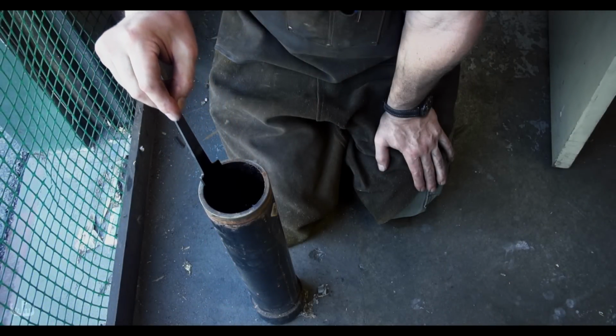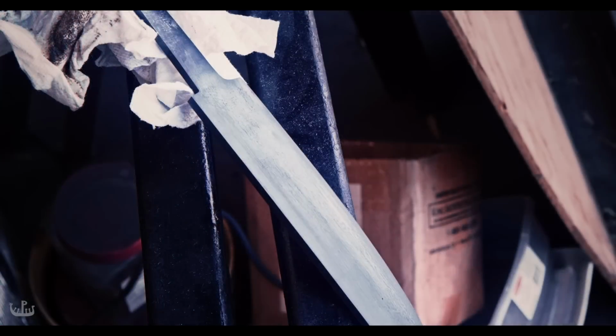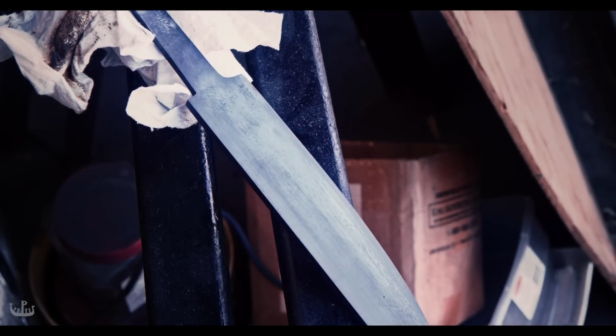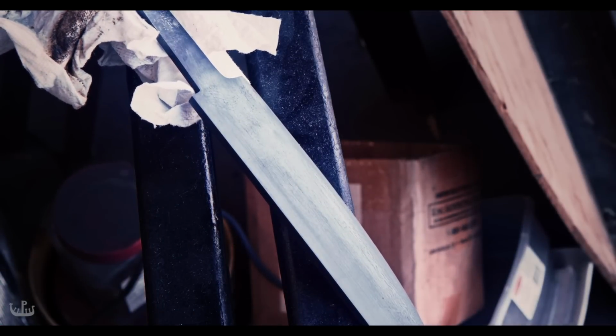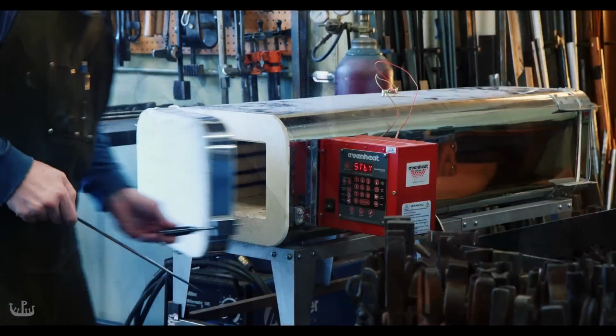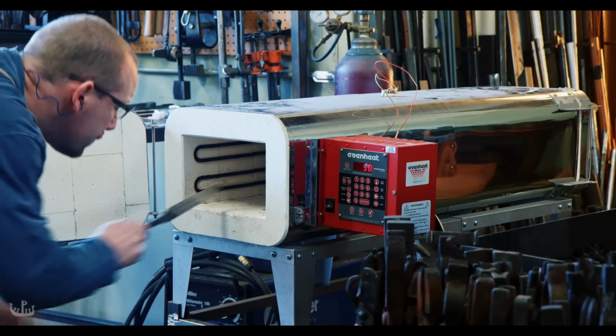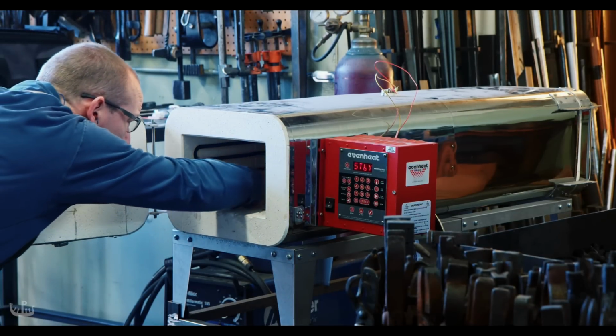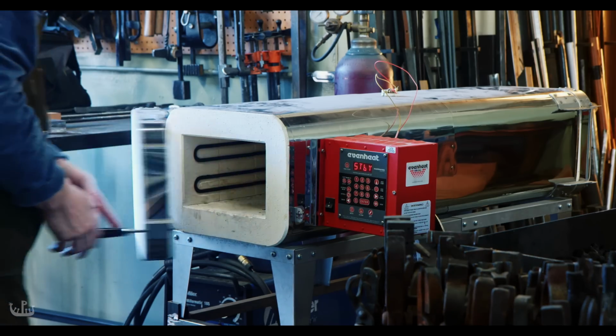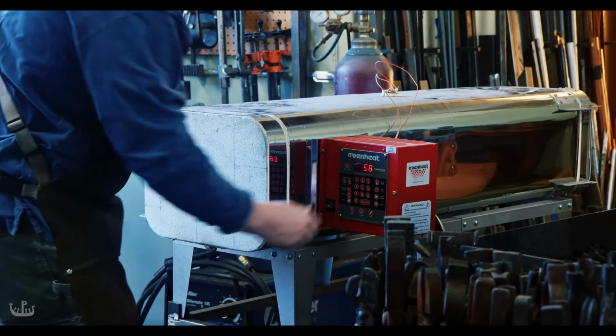Patience is a virtue, one that I do not always possess, so let's take a look at the pattern. The edge in ferric chloride shows nice carbide patterns. To increase the toughness of the blade, I'm tempering it at 500 Fahrenheit for an hour. That's about 260 Celsius.